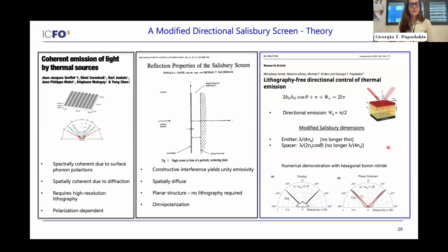However, this approach is polarization dependent. And the reason why it's polarization dependent is because surface phonon polaritons can only be generated for transverse magnetic polarization. Also, it requires high resolution lithography. And it requires a material that has a negative permittivity.